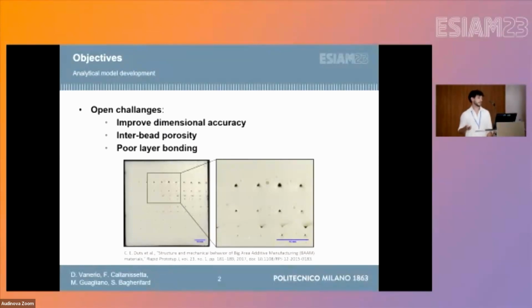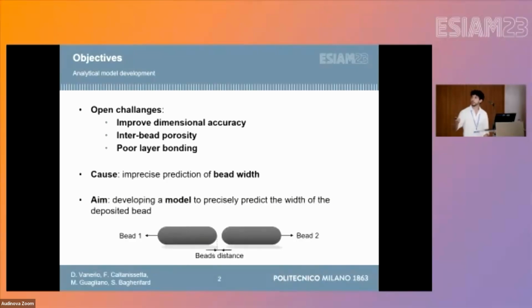The objective of this study is to face some of the open challenges for this technology, which are the improvement of the dimensional accuracy and, even more important, the reduction of the interbit porosity and the increase in layer bonding, so avoid poor layer bonding. In the image, you see some typical interlayer porosity.